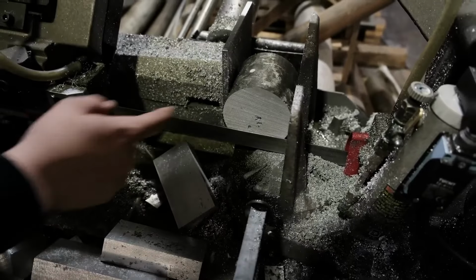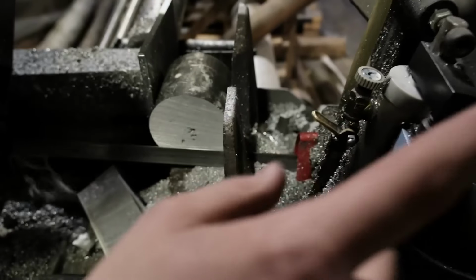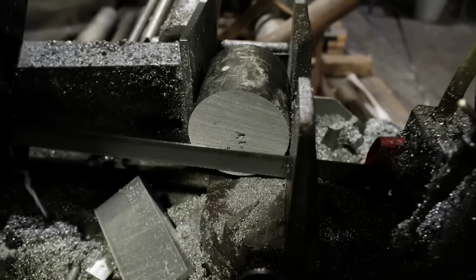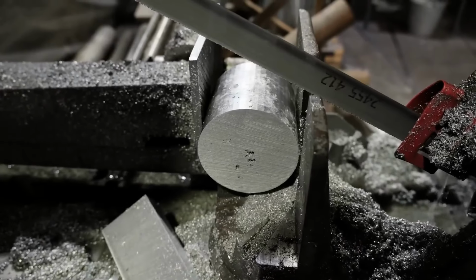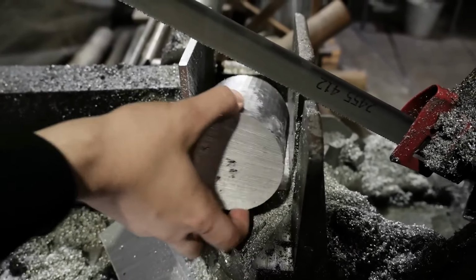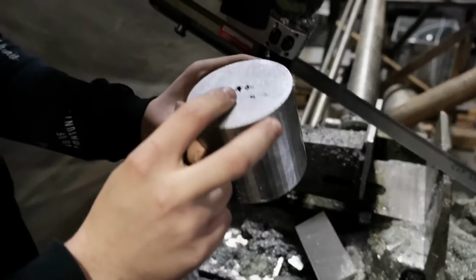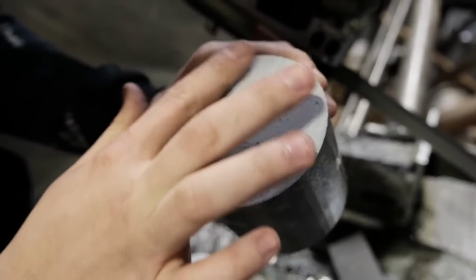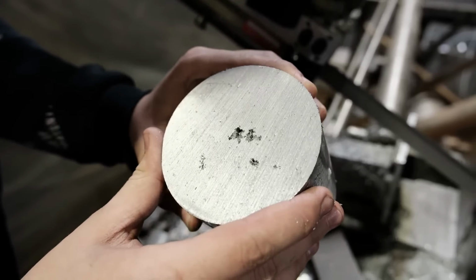Tada, we can see a cavity here, which is a type of casting defect. This cavity is quite deep, mainly due to shrinkage that happened during the cooling process. The sprue, which is the channel through which the molten material was poured, was made incorrectly. The shape of the sprue needs to be changed.